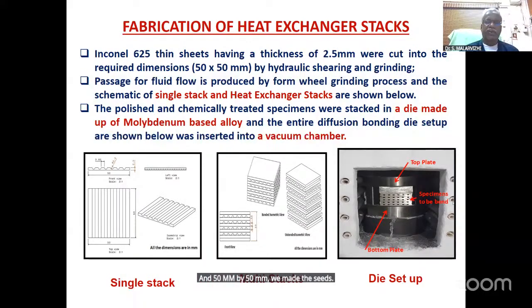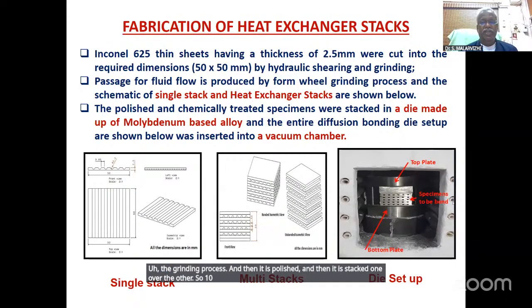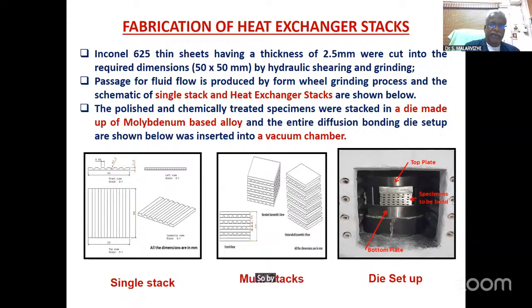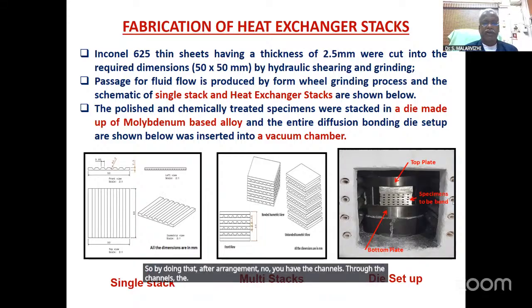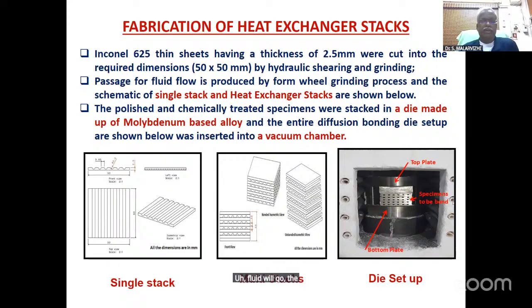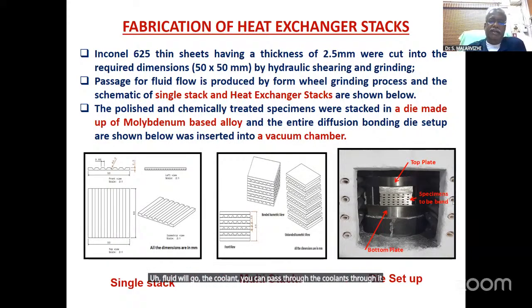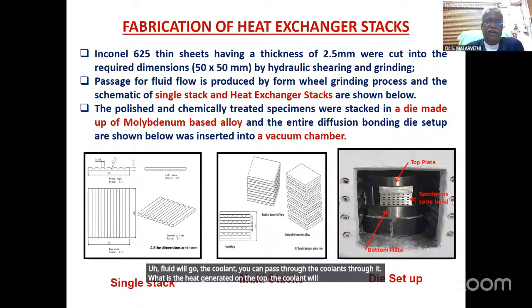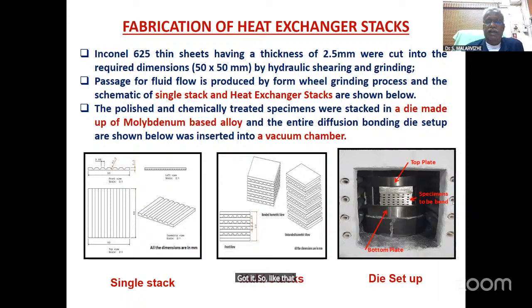In the sheet, for the fluid flow, we produce the keyways using the grinding process, and then it is polished, and then it is stacked one over the other. So 10 plates of each 2.5 mm are stacked one over the other. So by doing that, after arrangement, you have the channels. Through the channels, the fluid will go, the coolant. Whatever heat is generated on the top, that coolant will absorb the heat. So one end is the cool end, the other end is the hot end. So like that, this is used in the electronic industry.